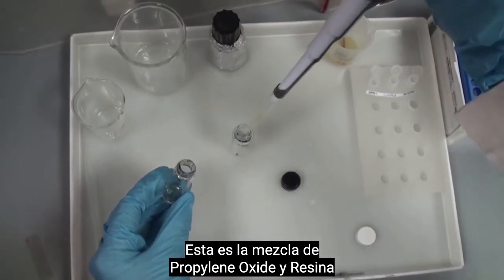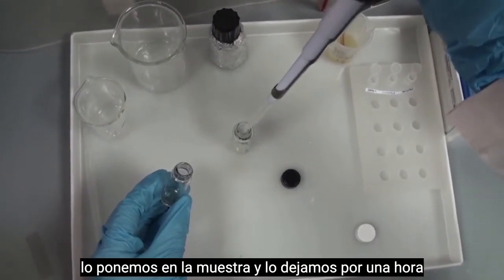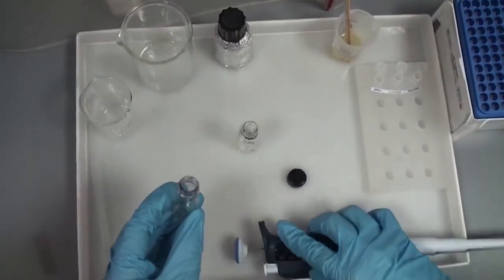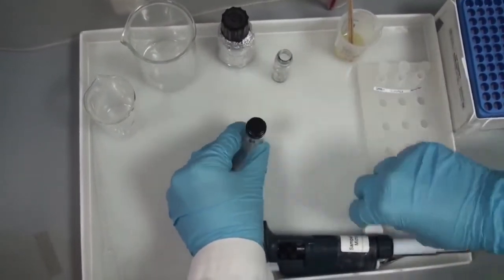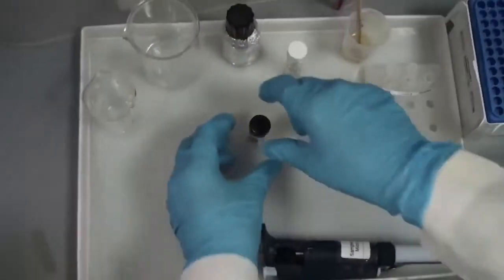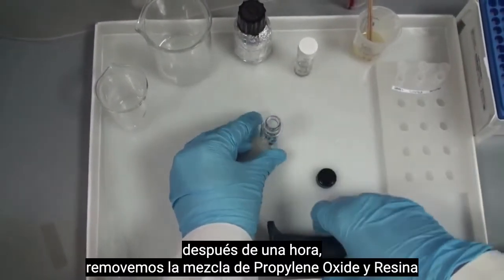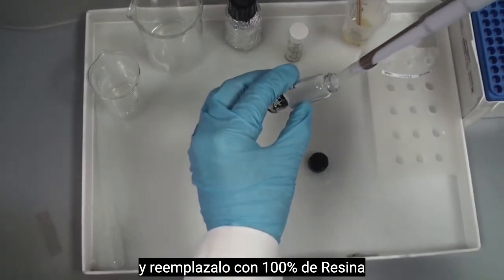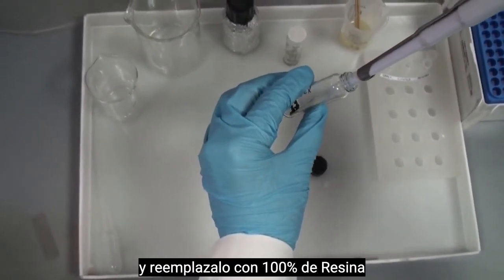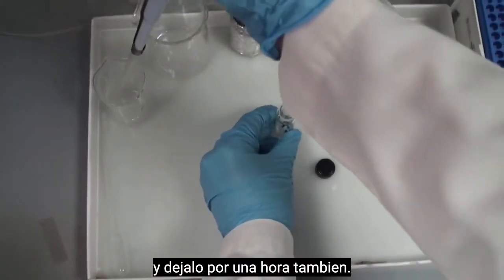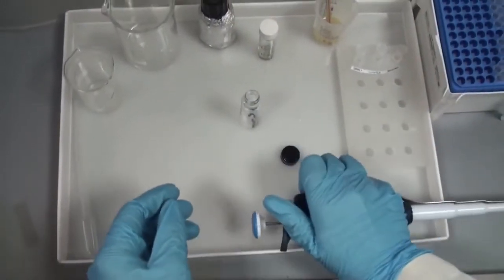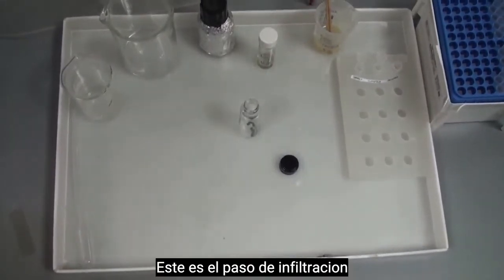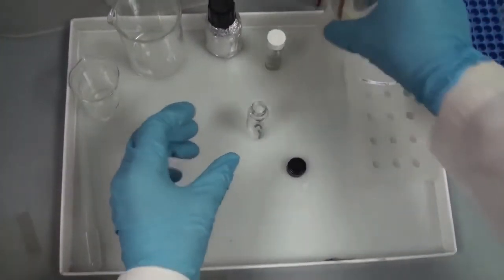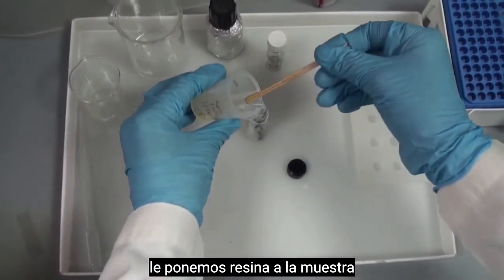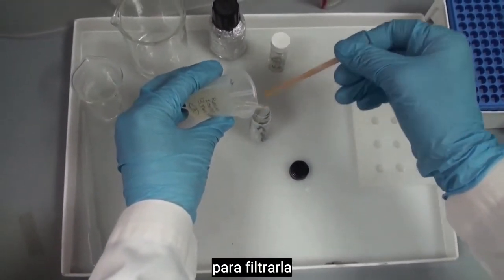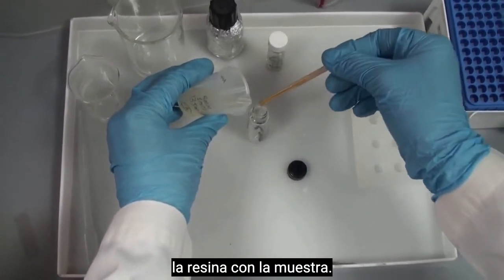This is the mixture of propylene oxide and resin. We put it on the sample and leave it for 1 hour. After the hour, we remove the mixture of propylene oxide and resin and replace it with 100% resin and leave it for 1 hour also. This is the infiltration step. So we put the resin on the sample to infiltrate the resin within the sample.